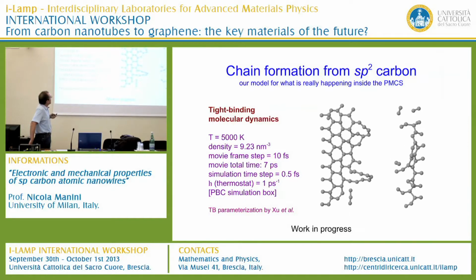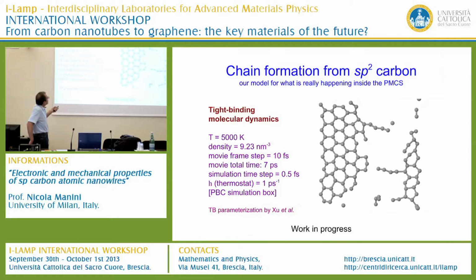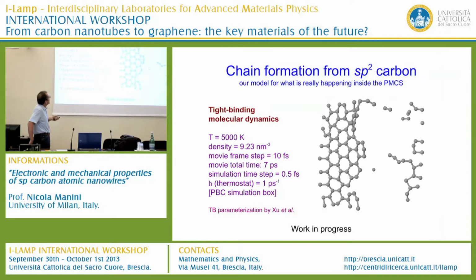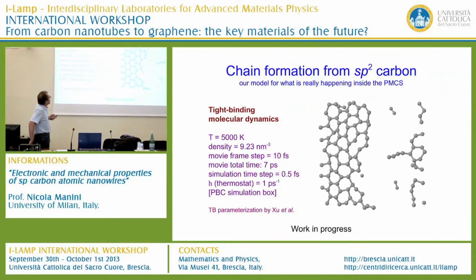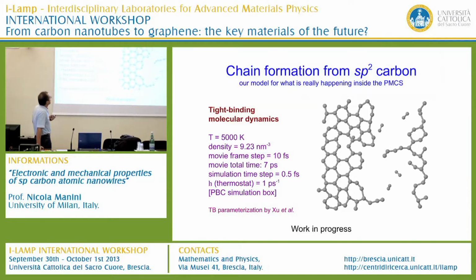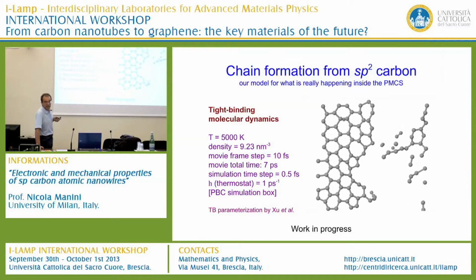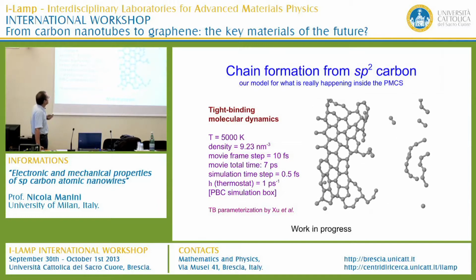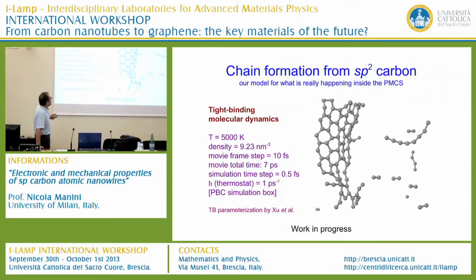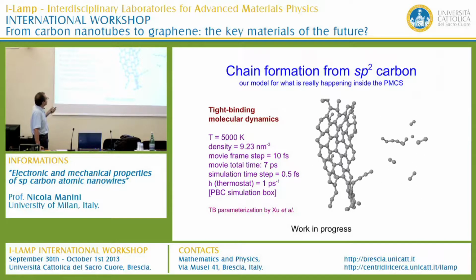And you see that some atoms get eroded away, that they form some single atoms, some dimers moving around, and also occasionally some longer carbon chains, as will happen here at the end. This will detach from the rest of this otherwise sp2 structure. So this would be an example of many simulations that we ran of the formation of those carbon chains, as is done in this plasma source that I showed you.